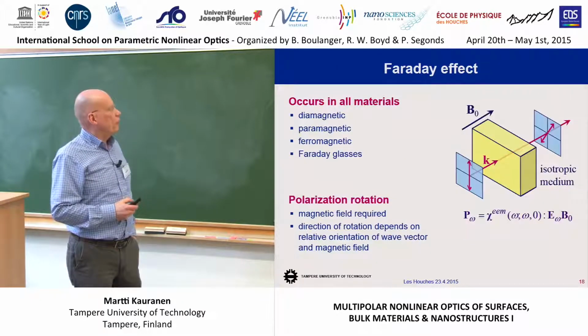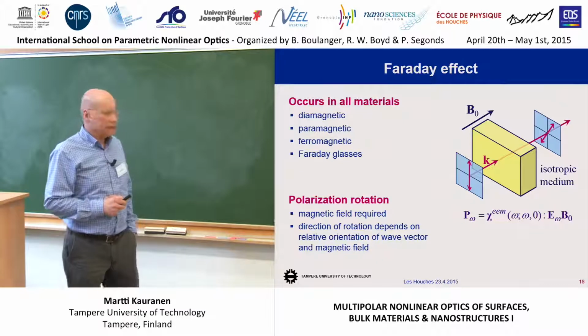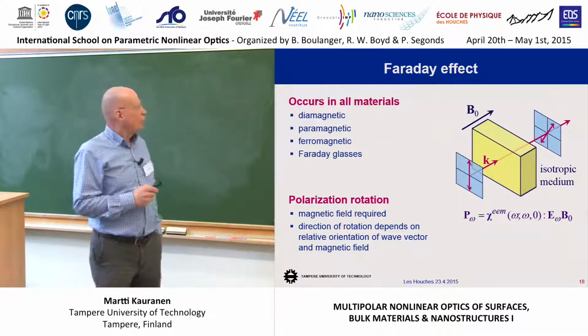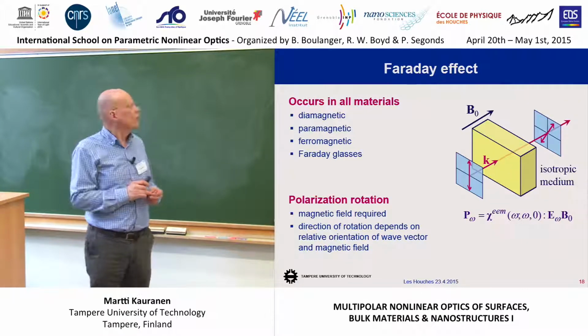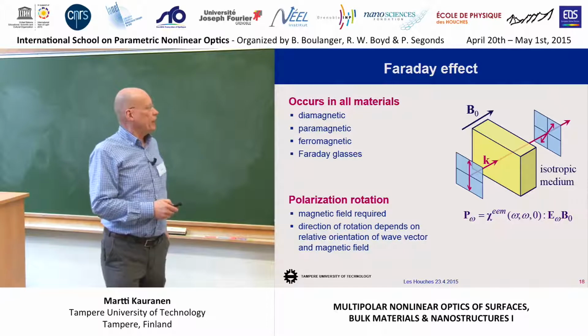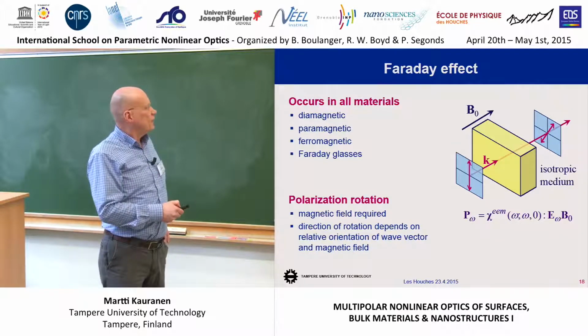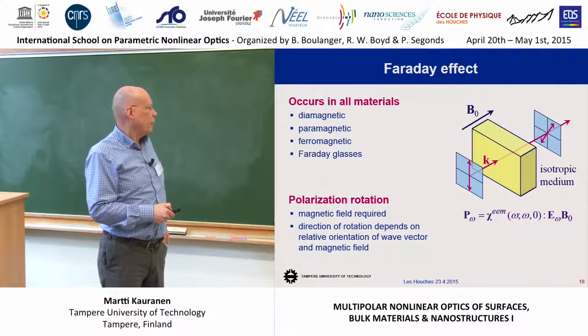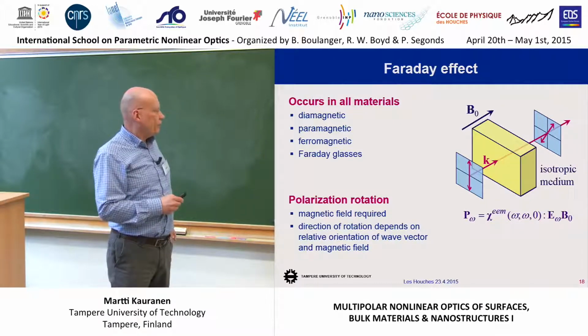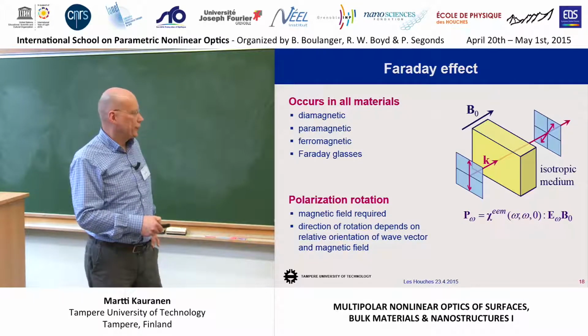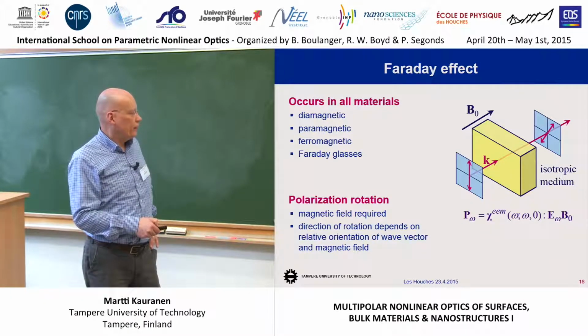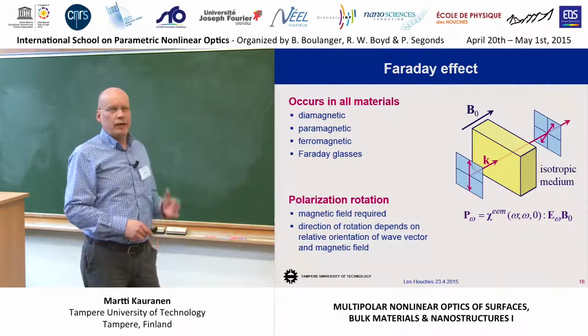Another way to rotate polarization is the Faraday effect, which in principle can occur in all materials. But of course, people are working hard to find materials that would have a strong Faraday effect. And what happens in the Faraday effect is that you apply a static magnetic field across your material along the direction of propagation, and then, for example, linear polarization would be rotated, even if the material itself is isotropic. And it turns out that the Faraday effect can be interpreted as an EEM-type nonlinear response, where the magnetic interaction is at zero frequency.